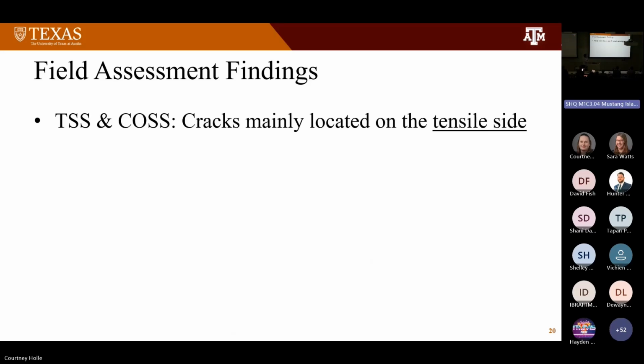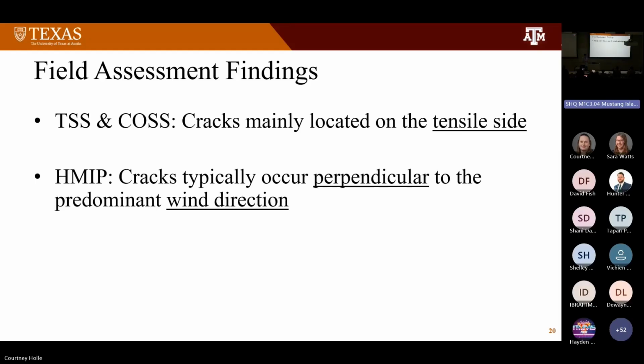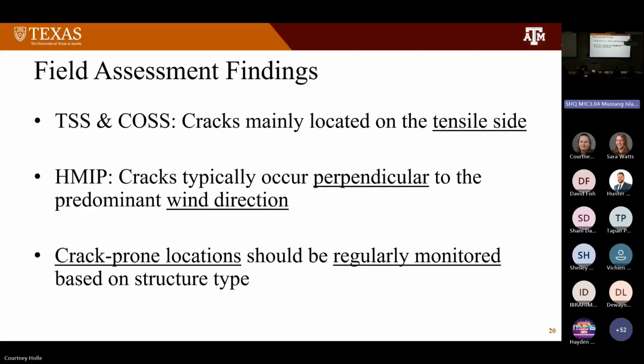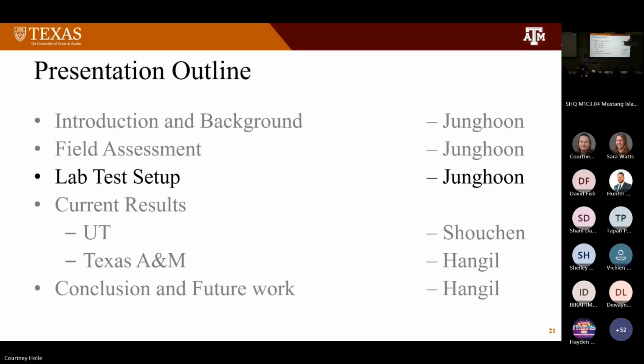So the findings from the field assessment are: for TSS and COSS, cracks are mainly located on the tension side, and for HMIP, cracks mainly occur on the side perpendicular to the predominant wind direction. And now we know where the critical weak area is, so we can focus our monitoring more effectively. Let's move on to the lab test setup.